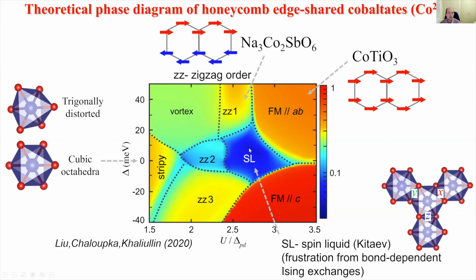I see. And another material that's in this phase diagram is this sodium cobalt antimony oxide, and that's here. Now it turns out that the crystal field splitting is almost similar between the two, so they're probably similar somewhere on this line, both of them. We don't know where this one is, whether it's close to this boundary or further away, but both of them may be similarly away from this phase.